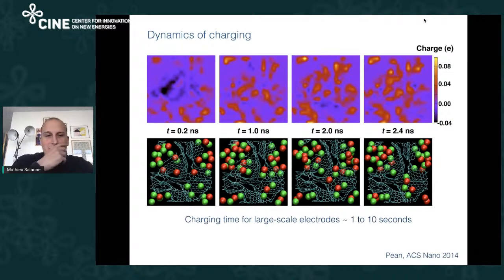And so what we could see is that, in fact, at short time scale, you tend to charge the big pores. And at longer time scales, you will have some exchange of ions between the pores, and you start to increase the number of ions that go inside the very small pores.